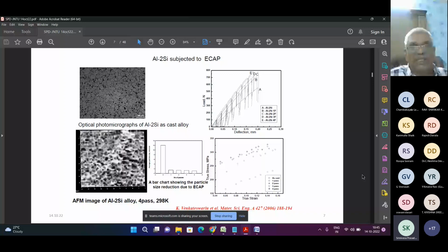Now you can see an optical photomicrograph showing the as-cast alloy with a beautiful grain size, and you have the micron bar so you can easily get the grain size, and you can see how the silicon particles are distributed. And when we have done this by ECAP, you can see an AFM image after 4 passes at room temperature.